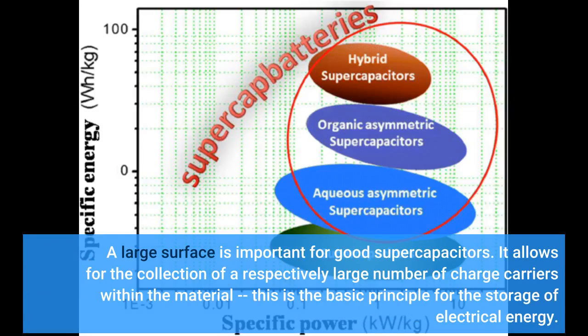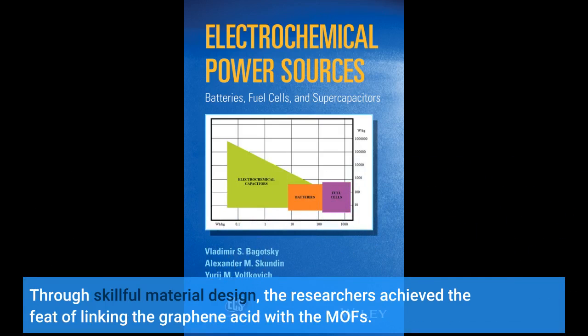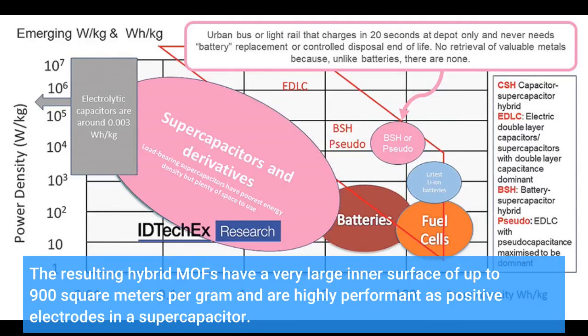A large surface is important for good supercapacitors. It allows for the collection of a respectively large number of charge carriers within the material. This is the basic principle for the storage of electrical energy. Through skillful material design, the researchers achieved the feat of linking the graphene acid with the MOFs. The resulting hybrid MOFs have a very large inner surface of up to 900 square meters per gram and are highly performant as positive electrodes in a supercapacitor.